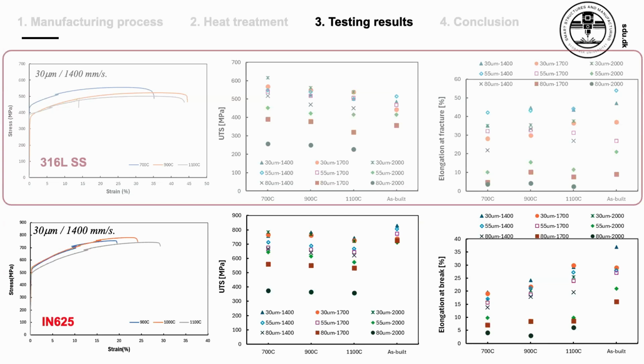Moderately, like a small effect on the UTS, but kind of a visible effect on the ductility of the material. And if we look at only one case, for example, if we look at only the 700, we can even see the effect of the single process parameter as well. For example, this case refers to a layer thickness of 80 micrometer and a scanning speed of 2000, which means the quality of the part should be lower, as we can see here.